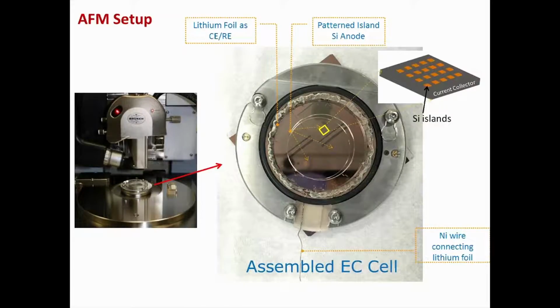Teddy showed you some of the AFM setup, but this is one of my own cells which I built there. What you can see is that there are two electrodes here. One is our silicon island electrode, which you can see, and the lithium is on the top, just below the glass window, which is acting as both counter electrode and reference electrode.